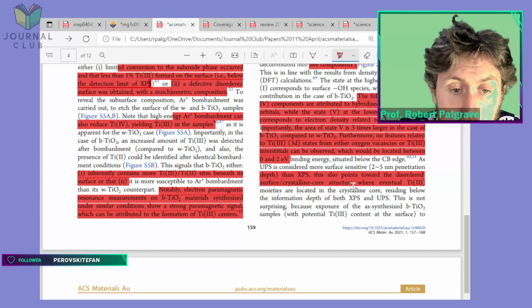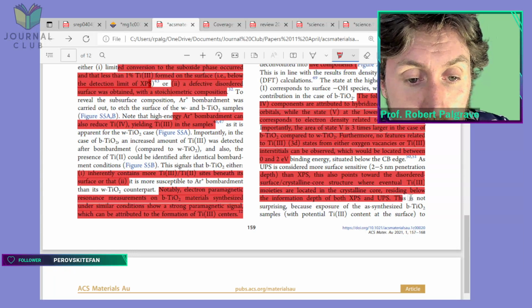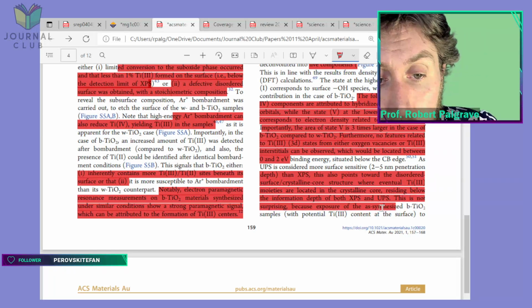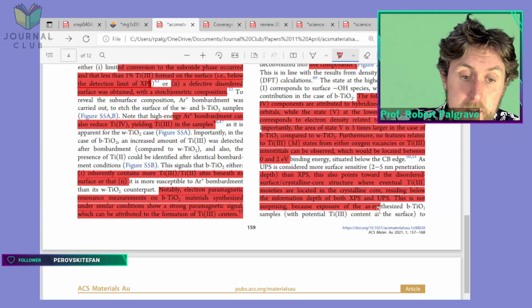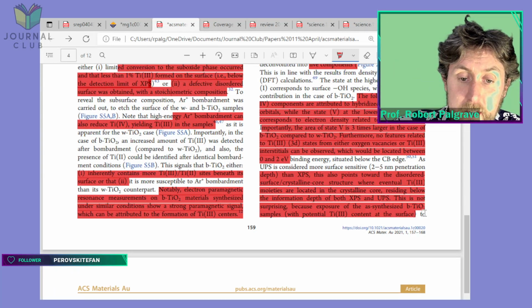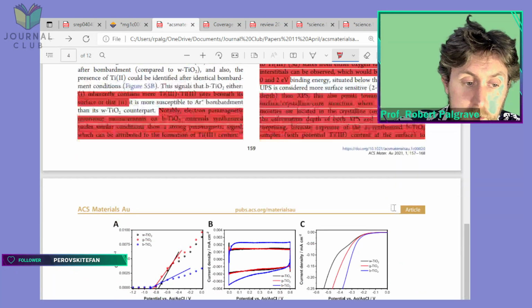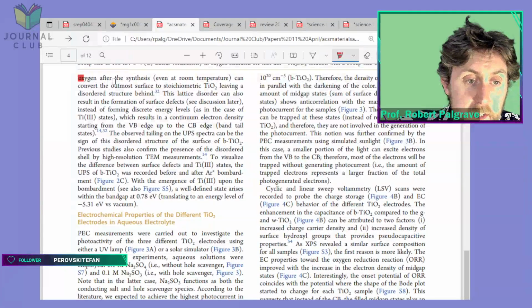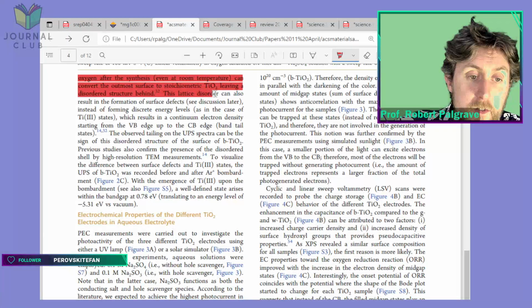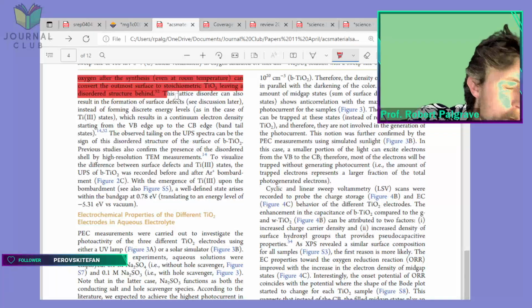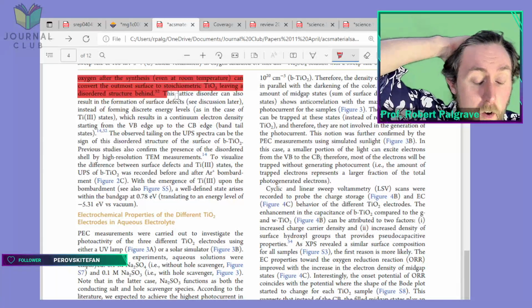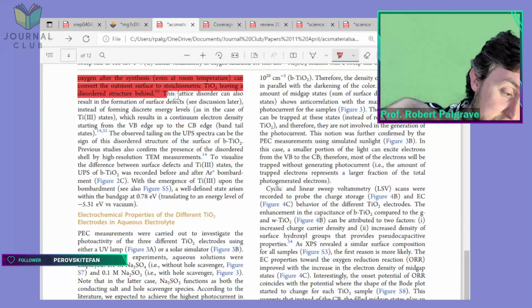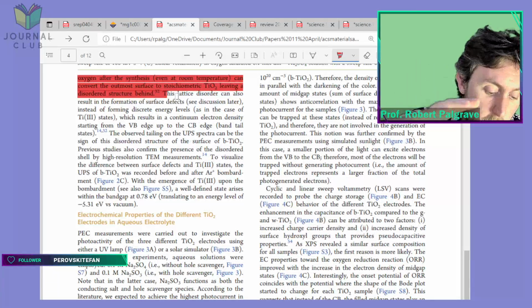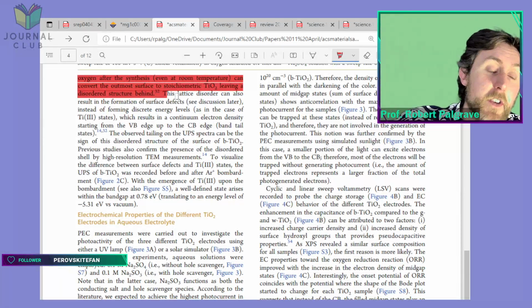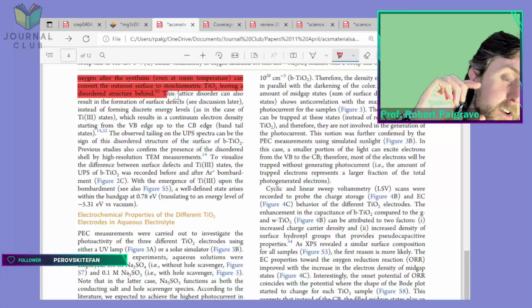It also points towards a disordered crystalline core structure where the Ti3+ moieties are located in the crystalline core, residing below the information depth in both XPS and UPS. This is not surprising because the exposure of the as-synthesized black TiO2 samples to oxygen after the synthesis, even at room temperature, can convert the outermost layers to stoichiometric TiO2, leaving a disordered structure behind. Okay, that's interesting. So they're saying that they're definitely on the conclusion that the Ti3+ is there, it's what's causing the visible light absorption, but it's buried underneath the information depth of XPS, sorry.